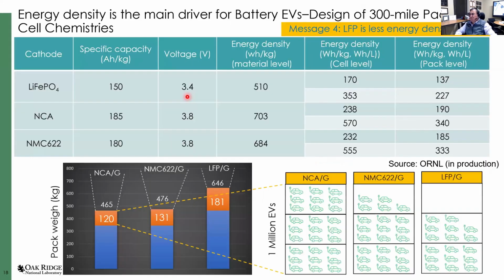The fourth message is that LFP is less energy dense compared to other materials like NCA, NMC. In this chart here, I'm showing the energy densities of the different materials, especially versus the layered oxide materials. And you can see for designing a 300-mile pack with those three chemistries, you need a lot more LFP.